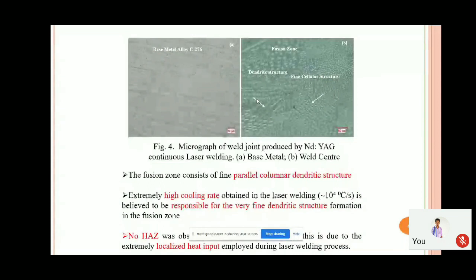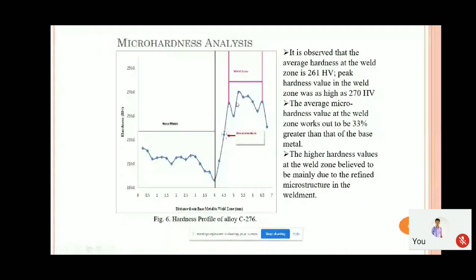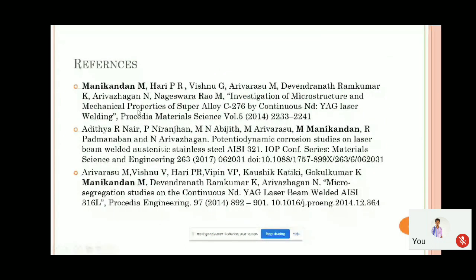Here we observe that the microstructures are very fine. So it leads to higher tensile properties as well as higher micro hardness as compared to the TIG welding process. I got tensile properties almost the same as the base metal property. It is really very interesting, and I'm getting a very good result as compared to the TIG welding process. You can find this publication; this is my reference, my article on the laser welding process.